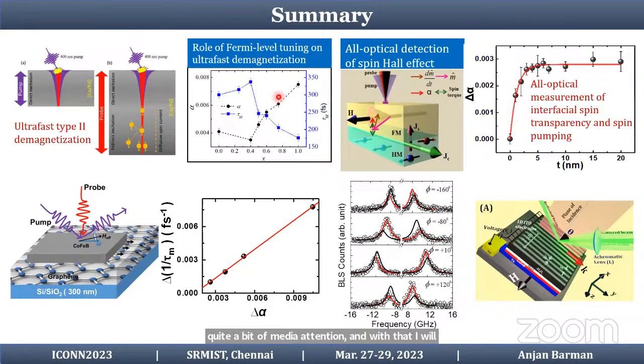So I have explained to you the different mechanisms of ultrafast demagnetization from spin transport and spin flip scattering processes. I have shown you the spin Hall effect and spin pumping effect measurement by using all optical techniques. I have shown you the 2D material ferromagnet spintronics, and I have also shown you the interfacial Dzyaloshinskii-Moriya interaction, as well as voltage controlled magnetic anisotropy based magnonics. So